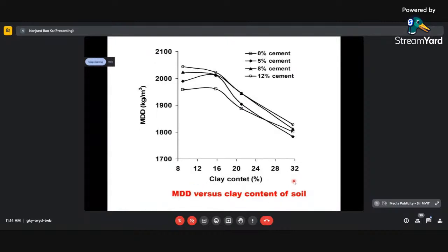This is again trying to show you the maximum dry density versus clay content. What is happening for different cement contents, that is 0, 5, 8, and 12%. So as the clay content increases, the density that is achievable keeps reducing.